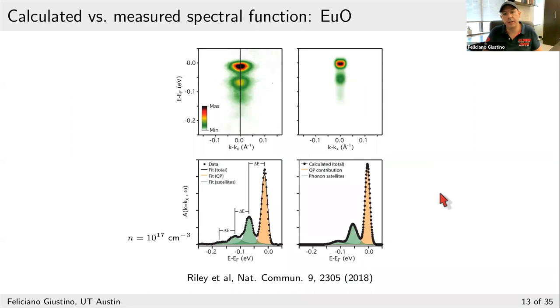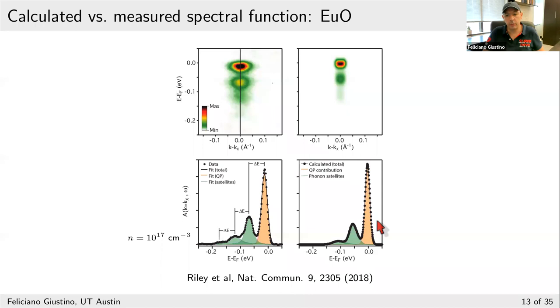As another example for europium oxide, calculations performed by Fabio Caruso show the spectral functions in the Fan-Migdal plus cumulant method. Taking a line cut at the conduction band bottom and plotting along the energy axis, you see the quasi-particle peak as the first peak in yellow, then the first satellite, then the second satellite. The calculations show a similar phenomenology. There is still work to improve the intensity of satellites, but I will move on and mention what comes next.